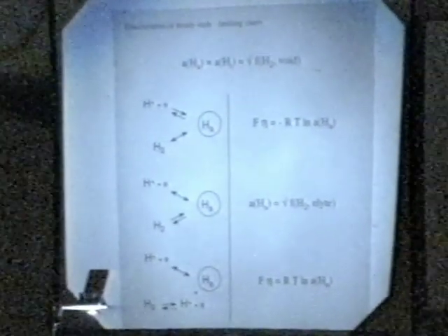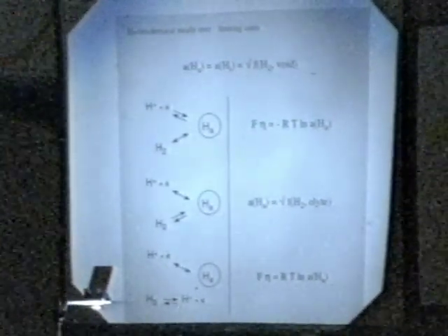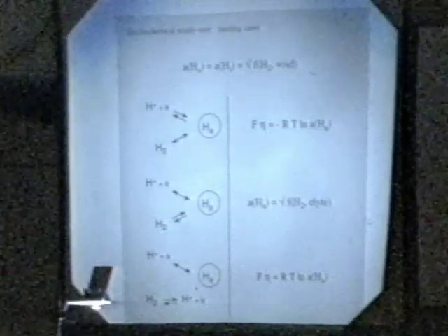What I'm going to do is deal with extreme cases. I'm not going to deal with intermediate cases. We can break the electrochemical reaction mechanisms down into three sets. When we drive an electrochemical process, we can, in the limit, as an extrapolation, assert that one, but not both, of the electrochemical processes, and I'll express this loosely, requires a great deal more pushing than the other. The one that requires the least amount of pushing, we will state, is in a state of quasi-equilibrium.